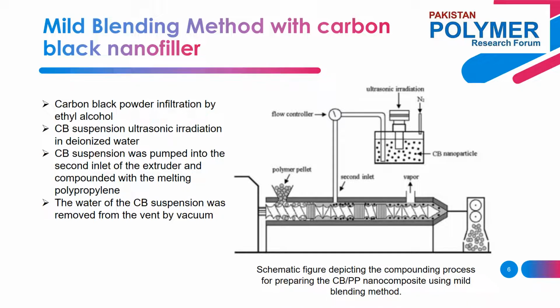in the compounding zone. The water content of the carbon black suspension was removed from the vent by vacuum to obtain the nanocomposite. Finally, the extrudate was thermally compressed to prepare samples for complete characterization of the nanocomposite.